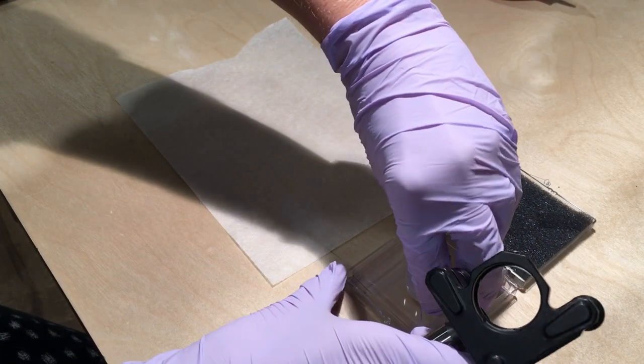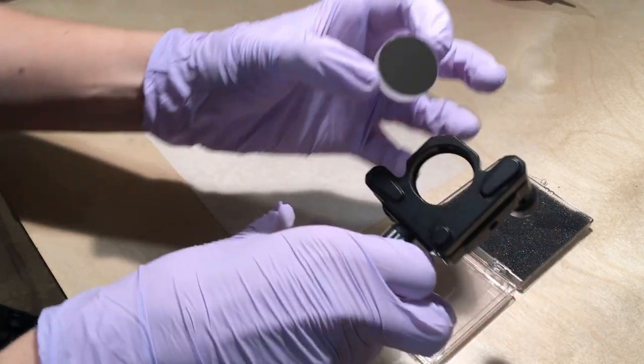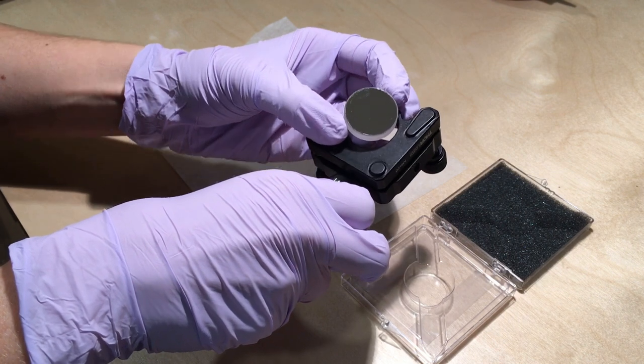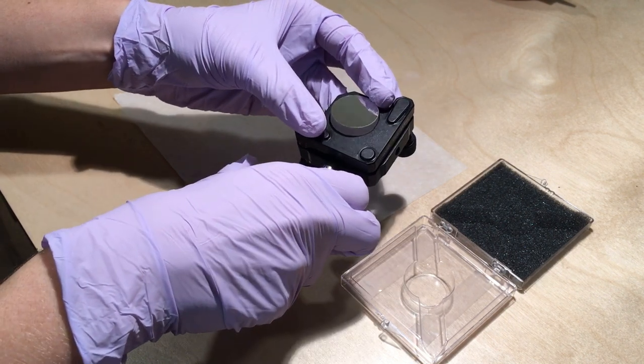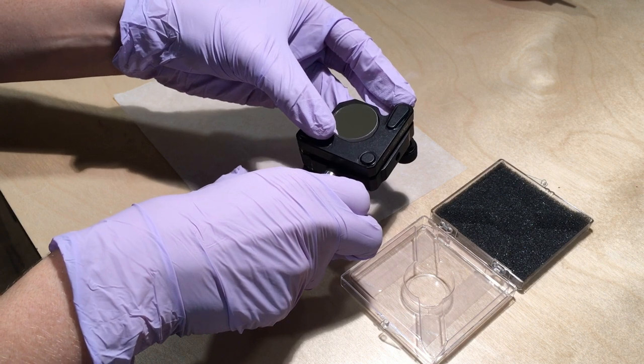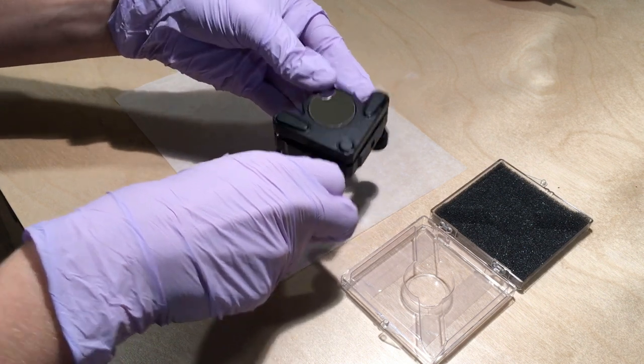The next mirror we tested is silver. Unlike gold, silver has high reflectivity in the blue. Unfortunately, silver tarnishes in atmospheric conditions and must be protected with a dielectric coating. Our test mirror has a single layer of silicon dioxide.